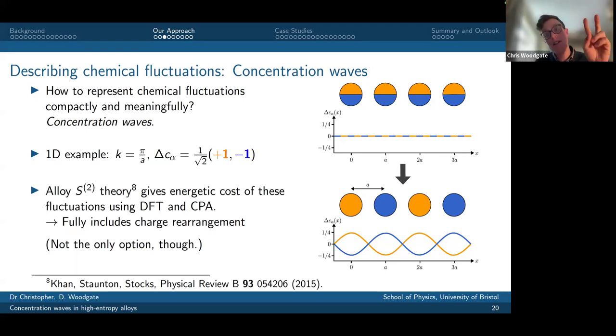So actually, there are 2 things. We use a Landau theory for an initial estimate, but there's also the recovery of an effective pair interaction. Well, the difference between Landau and Landau-Ginzburg theory: in Landau-Ginzburg theory, they allowed a gradient square term, so they allowed the order parameter to fluctuate weakly. The leading order fluctuations around the uniform state are described by Landau-Ginzburg theory. So you can describe a correlation function of the order parameter field. And it seems to me that this is exactly what you're doing here, right? Yeah, absolutely, this is exactly what we're doing. Right, wonderful. Excellent. Thank you.